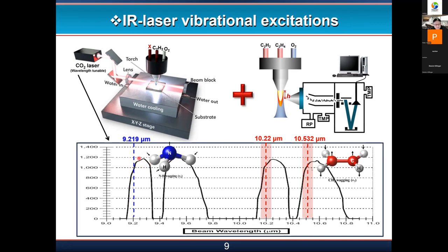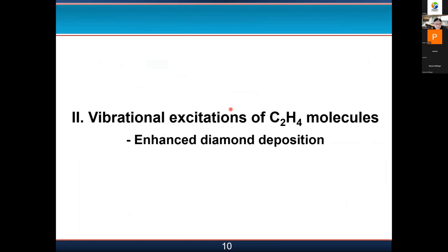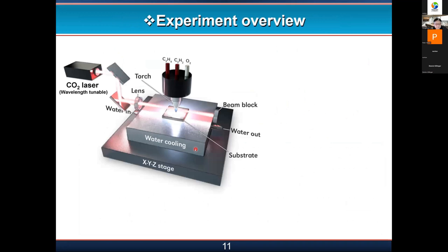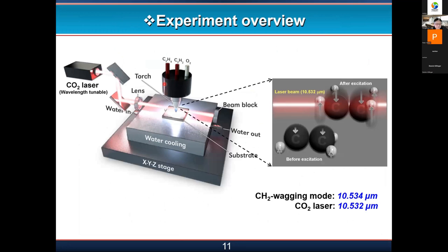So 4 bands give us some accessibility to the vibration modes of precursor molecules. One example is that we can excite the vibration mode of C2H4 molecules to enhance diamond growth. In this combustion flame, we use oxygen and acetylene in the chemical reaction. The precursor, the C2H4 molecule, has a vibration mode at 10.534.